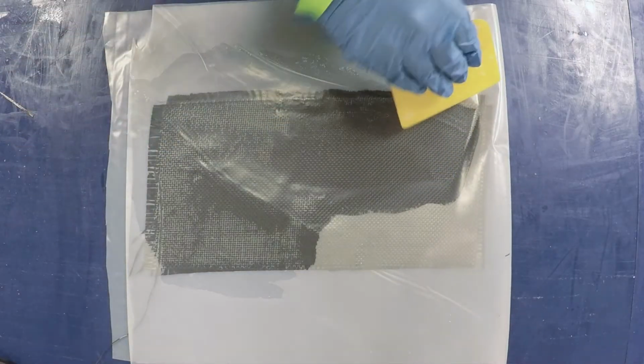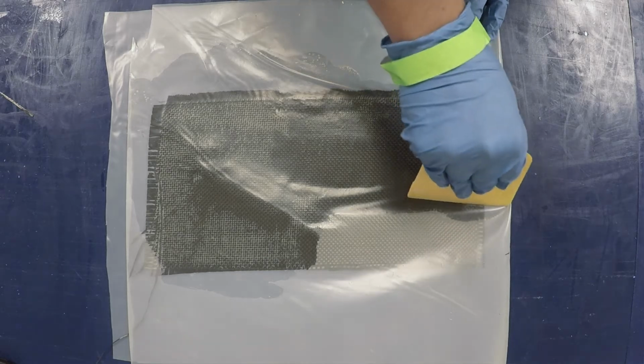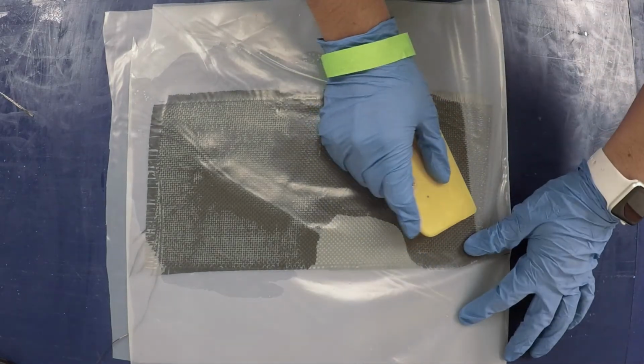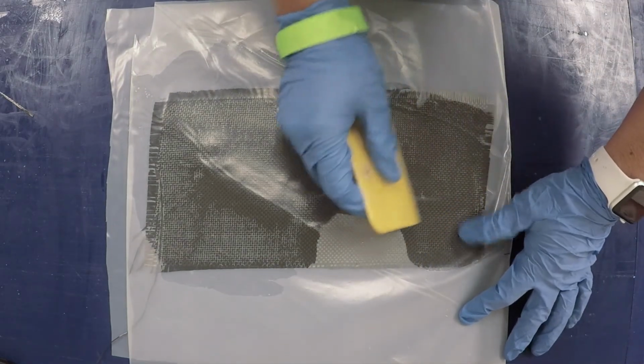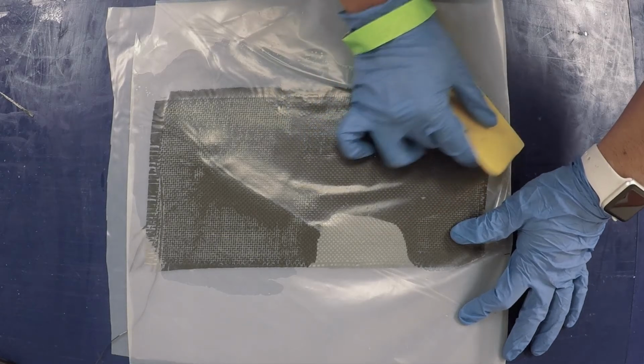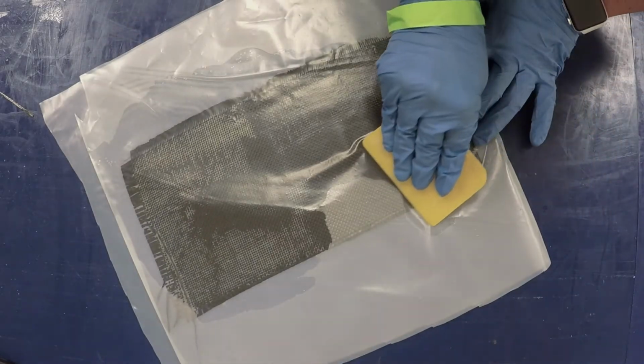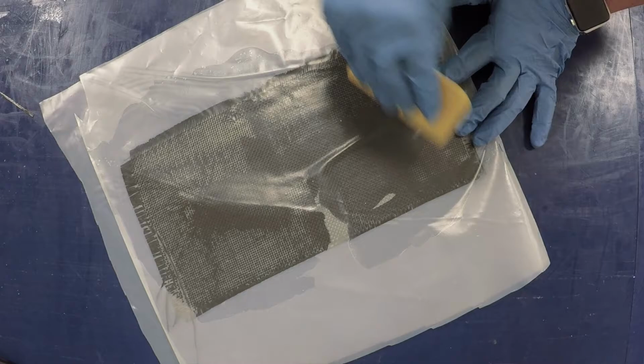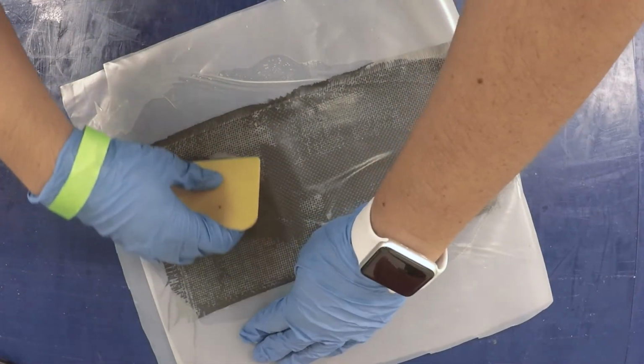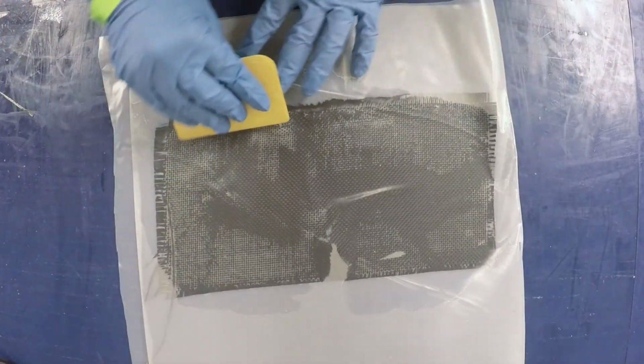The goal of this process is to saturate the fibers and then remove any extra epoxy that can be removed by the squeegee. Oversaturation doesn't mean a stronger result. If anything, it's more likely to make a more brittle and heavier final product.